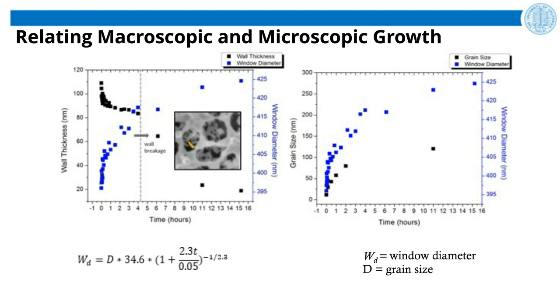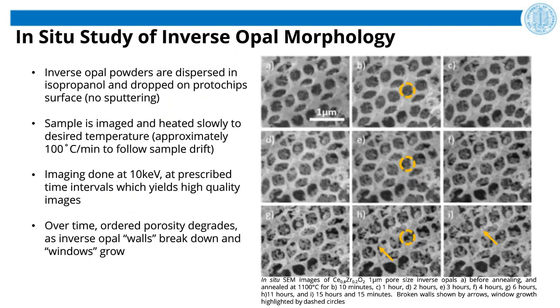I would like to return to this slide. The structure of the inverse opal was deposited directly on the Protochips surface. The sample was imaged with slow heating at 100 centigrade per minute. All images were taken using an accelerating voltage of 10 kV. The images clearly indicate that with time the structure undergoes significant degradation.